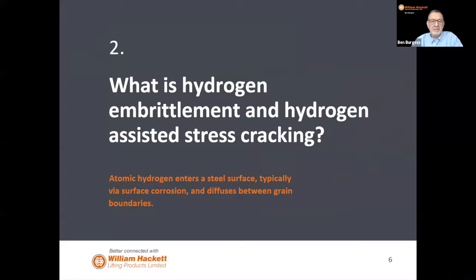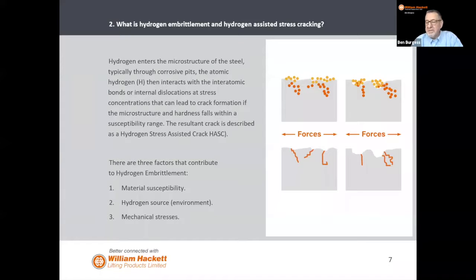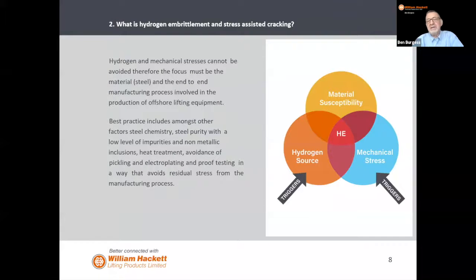So just to nail exactly what hydrogen embrittlement is, and hydrogen assisted stress cracking. Hydrogen embrittlement is the phenomenon caused through a loss of strength and toughness in the steel through the introduction of hydrogen into the material, thus making it brittle. If you look very carefully at the slides here, we've all seen chain and steel-based products offshore. You cannot control the corrosion that takes place. As the corrosion takes place on the surface, the hydrogen atoms diffuse into the steel, and as they do so, they create internal pressures. We don't believe this can be avoided, and therefore you have to look at the solution differently.